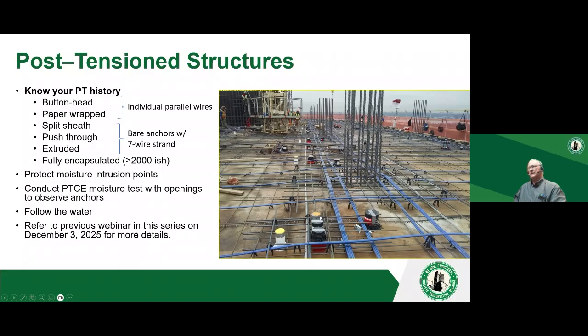Post tension structures, you've got to know your history when you get into that. This is a fully encapsulated system, but this is how it's laid out. Typically, you have banded tendons here. So this is your column strip, and then these are your distributed tendons. But you see, they put two of them side by side. Previously, they would lay them out individually. Then they have different systems, like in the 50s, 70s, they were your button heads, paper wrap systems, and they had individual parallel wires. So some of the older structures, you're going to have to deal with that.